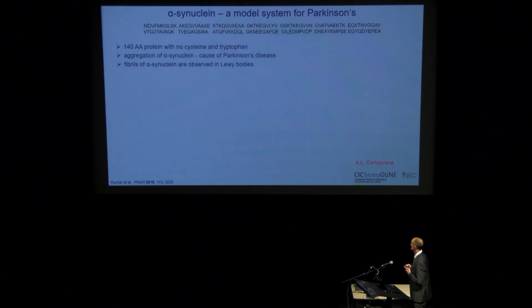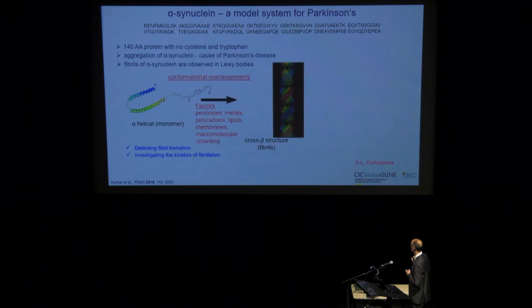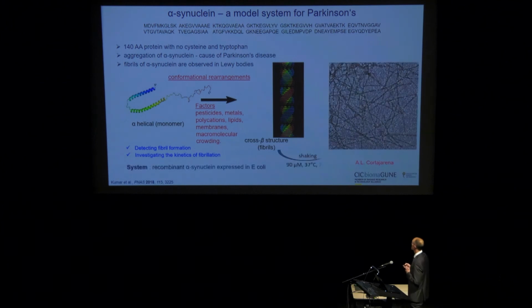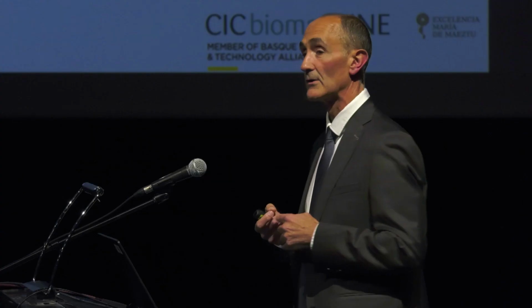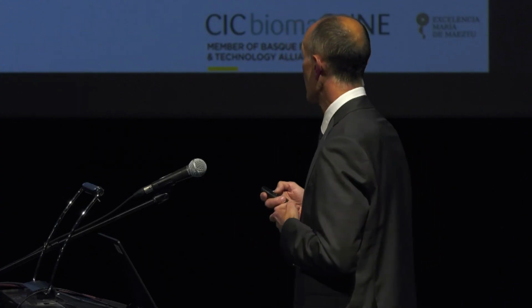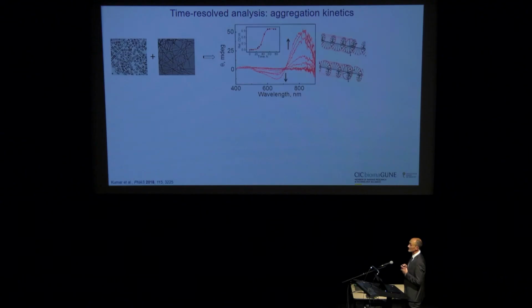And so we started working with a model protein, alpha-synuclein, that our colleague Aitziber Cortajarena could express from bacteria in our labs. And then by incubating the monomeric protein, we could obtain the amyloid fibers. And then what we did was incubating the fibers with gold nanorods and then measure circular dichroism. And as you can see here, over time, we could see an increase in the intensity of these CD bands